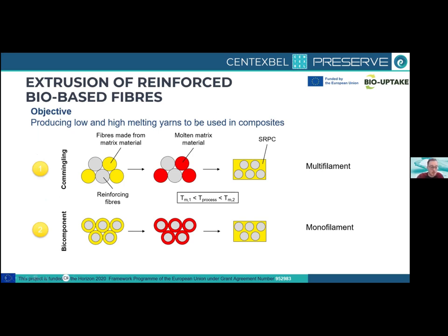And when you look at the first one, this is commingling, we make them separate. We make a yarn from a low melting temperature material and a yarn of a high melting temperature material. Then we combine them, we bind them together to make the composite, and then we melt it at a temperature that is between the melting temperature of the low one and the melting temperature of the high one. So you keep the strength of the high melting temperature yarn, and you melt the low melting one into the matrix of this composite. And then you get a very high strength composite.